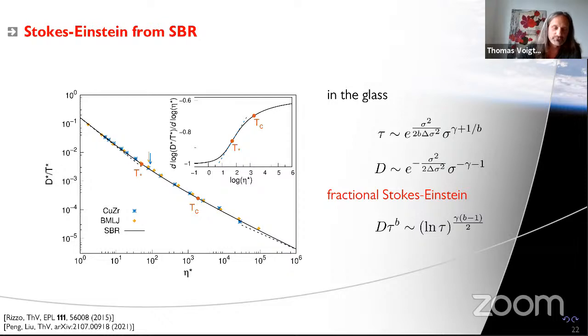Just as a reminder, we are used to the fact that in systems close to the glass transition, all the relaxation modes are really strongly coupled to each other. So basically that means that if I look at the diffusivity or at the inverse relaxation time, it's not a big difference. It's not a qualitative difference. So the way this is usually expressed is by saying that D times eta, or D times the structural relaxation time, is asymptotically constant. And a nice way of checking this is to just make a double log plot of the diffusivity versus the viscosity in proper dimensionless units. So you have to be careful to also take out the factor of kBT. And then if Stokes-Einstein holds, this should be a line with slope -1 here.